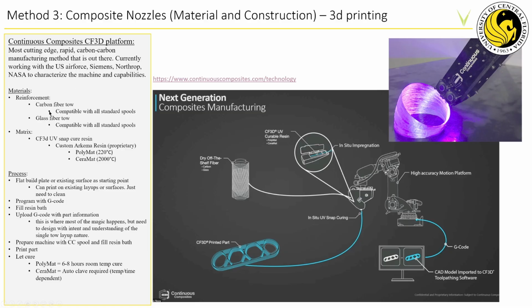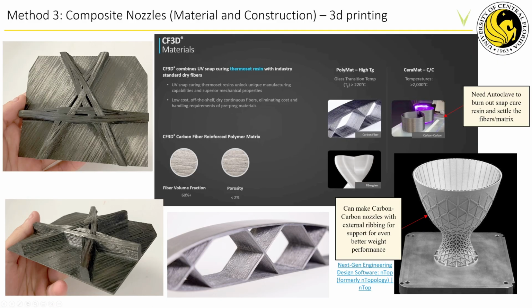And it can use different types of tow. It can use carbon fiber tow or glass fiber tow. And then the snap cure resin, there's two different main types, and you can kind of see the difference here. The first type is for more generic applications, where you can use whatever tow you want, carbon fiber or fiberglass, and then you use the polymer matrix binder, and then essentially you get a glass transition temp of less than 220 degrees Celsius. So you don't want to be using this for high temperature parts, but this is great for just normal structural parts. And then you actually have another type where you snap cure the part in place, but then you actually have to throw it into an autoclave afterwards, and then it becomes a full carbon-carbon part, where this is the real application for aerospace, where you can actually go ahead and use it for nozzles and different things.